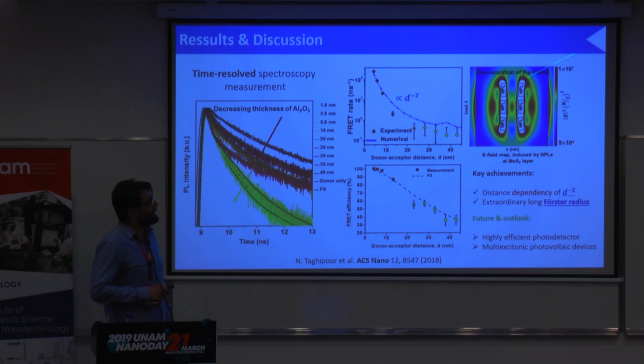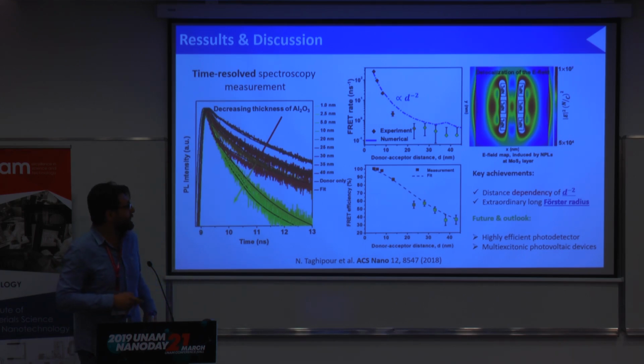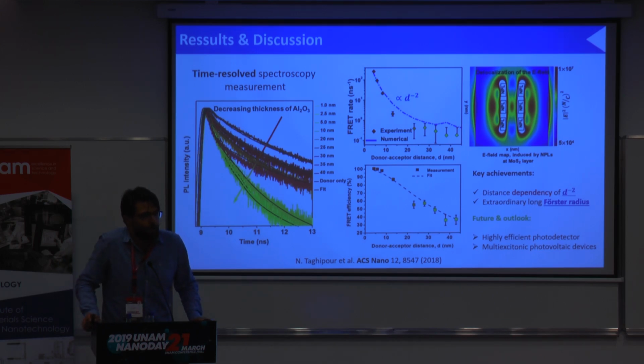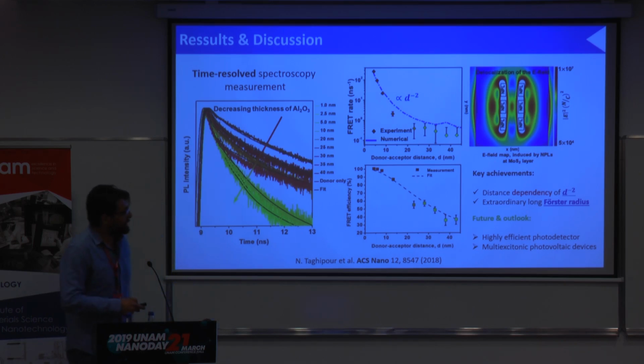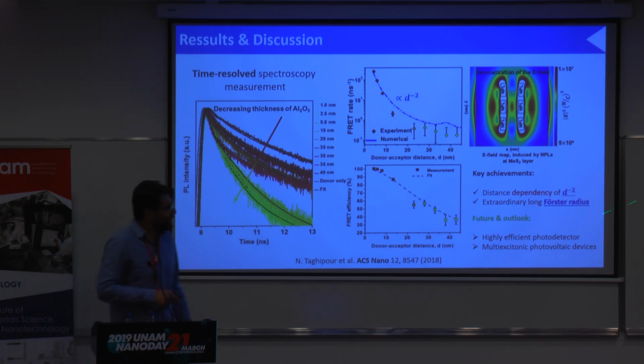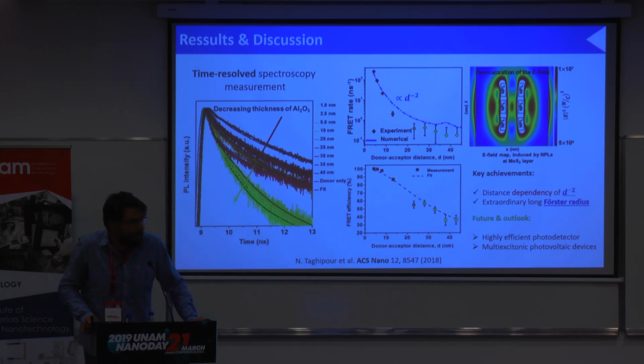In addition to these, thanks to the strong localization of the electric field in our donor layer and acceptor layer, we achieved, for the first time, d^-2 energy transfer. It opens new insights into the physics behind energy transfer in such a hybrid. And also thanks to the layer-to-layer dipole coupling, which comes from the geometry of our donor and acceptor, we achieve an extraordinarily long Förster radius, which we reported as 33 nanometers.